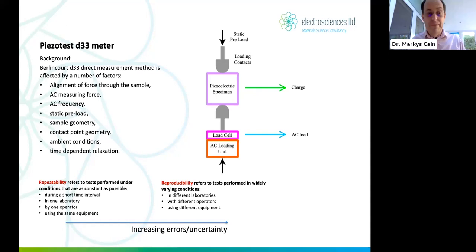Okay, obviously not. Sample geometry. That's very important. This technique, this piezo test Berlin-Court technique, was meant to be sample geometry independent. You just put any sample in there, and you'll get a decent d33 measurement. Contact point geometry. These loading contacts, should they be flat? Should they be hemispherical? Should they be balls? What's the best option there?